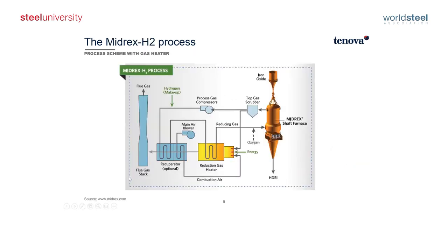Midrex, that is our competitor technology, developed a scheme also for operating with 100% hydrogen that is very similar to ours. The main difference is in the pressure at which the module operates. In the Midrex scheme, the module operates basically at ambient pressure. In the HYL module, we operate at 6 bar, more or less, and the operating temperature. But basically, you can recognize that the scheme is very similar.